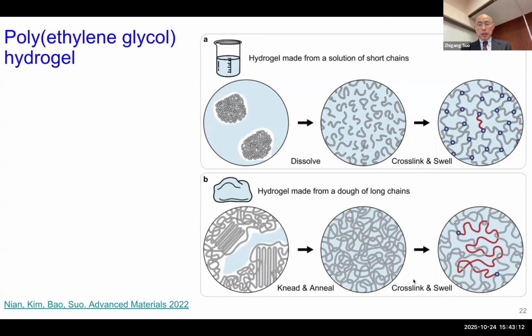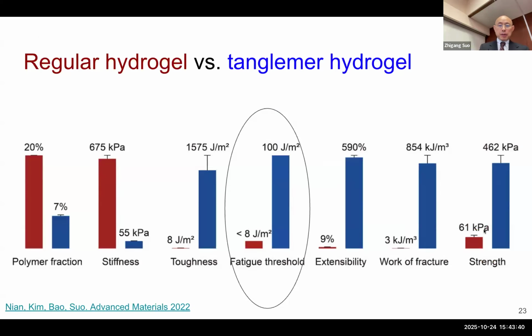I've already talked about this difference, and I showed you individually by comparison. So traditional material: short chain, no entanglement. Entanglement was not in people's thought in making this gel. We prepare very long chains, as long as we can buy, and then use very sparse crosslinks with lots of entanglements. That material gives you high toughness.